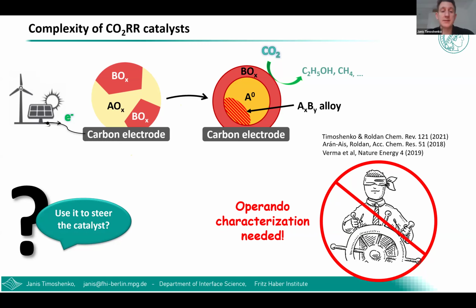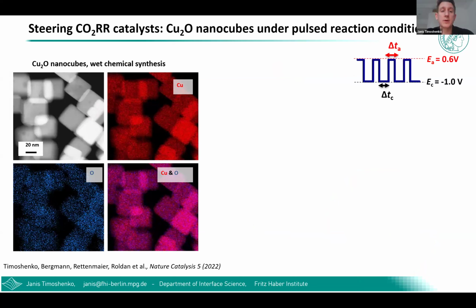So one nice example from a few years ago was related to, again, the CO2 electroreduction reaction, where we used copper oxide nanocubes as a catalyst. These are very nice, very monodisperse cubic-shaped catalyst particles, at least in the beginning, in the as-prepared state. And our idea here was to try to manipulate the properties of this catalyst by exposing it to pulsed reaction protocols.